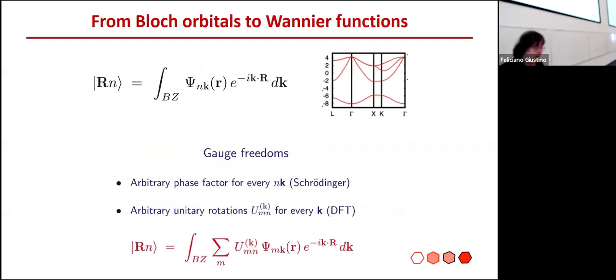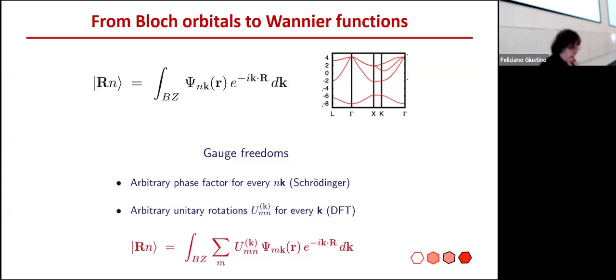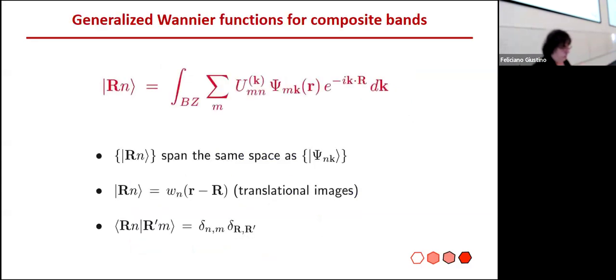In the most general Wannier transformation, not only do I integrate over the Brillouin zone with a phase, but at every K point I can mix all the states. For silicon or gallium arsenide with four valence occupied states, at every K point I can mix those four states with a 4×4 unitary matrix U, and then integrate each resulting combination over the Brillouin zone. The property of this transformation is that because it is unitary-unitary, we span the same Hilbert space as our original states.